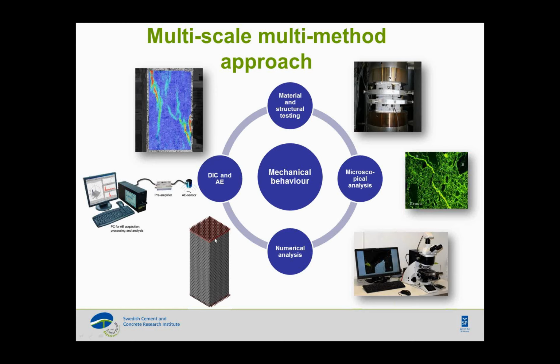What we got from microscopical analysis was that we had the diffusion of sulphate ions into the cement paste, but it was not all across the cross section. So we had more impact of this expansion at the surface and less when we moved into the cross section, and that was a formation of ettringite and the expansion of cement paste.